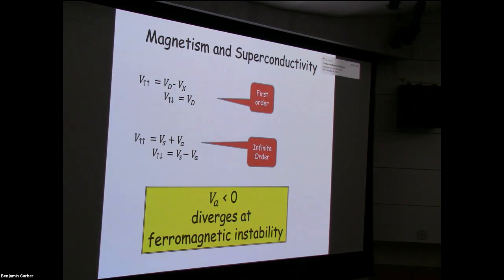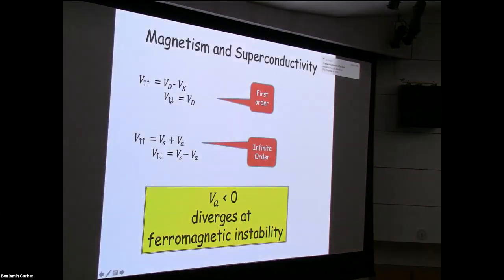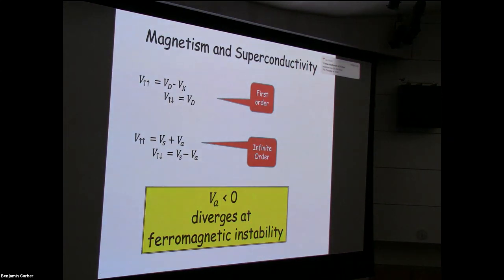And so this relationship between being close to magnetism and superconductivity is thought to explain the fact that many of the 4D transition elements, if you plugged in normal ideas about electron-phonon interactions, should be superconductors, but they're not, and it's blamed on magnetism, because they are nearly ferromagnetic. And similarly, the P-wave superconductivity of helium-3 is qualitatively thought to be associated with being close to magnetic instability.